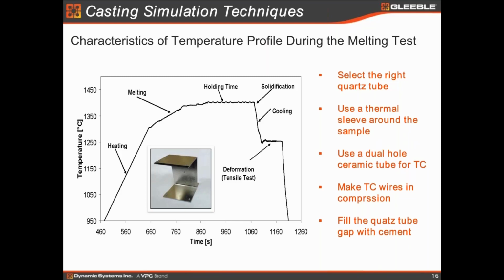My experience is that you would need to apply a compression stress onto the thermocouple joint. That way, when the sample is melted, the thermocouple will not be detached automatically, because you don't want to waste the test, right? So that's one experience that you would do. You could do it easily, because after you put the thermocouple onto the junction, you can just apply compression from the thermocouple. That's easy. But of course, there is another way that you can make it even easier. That is to use a cement.